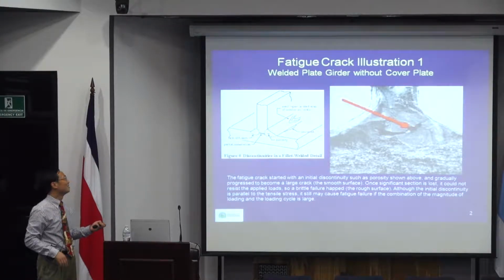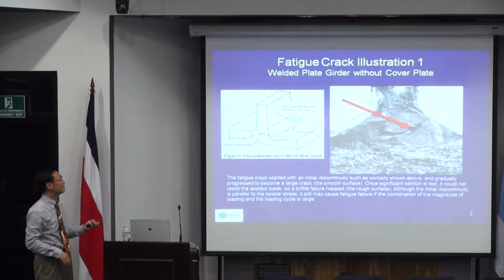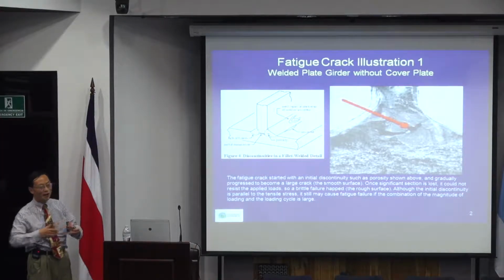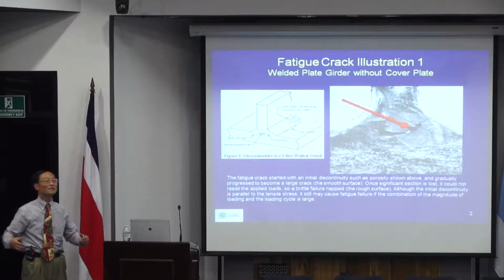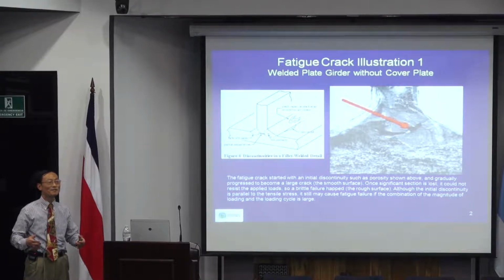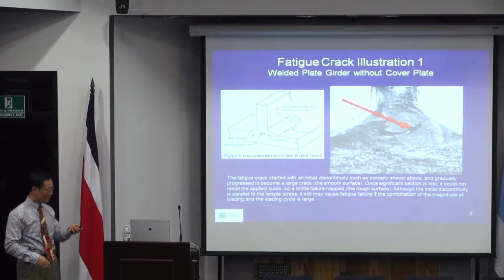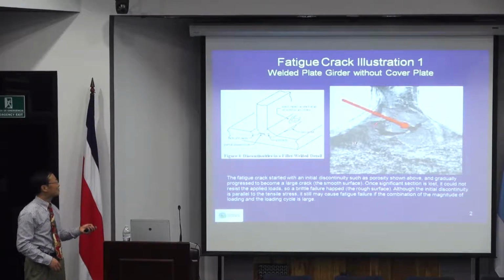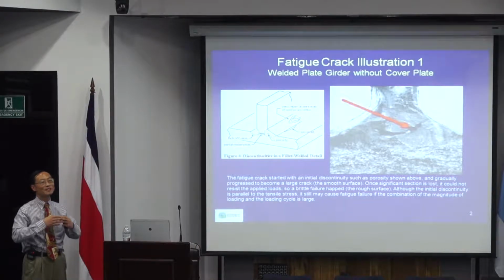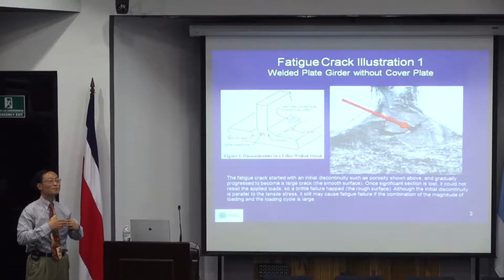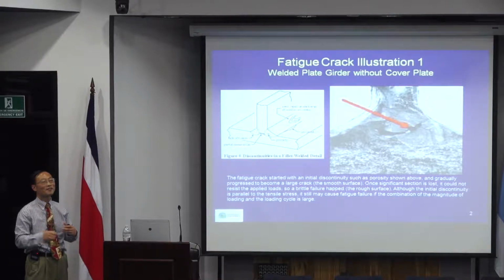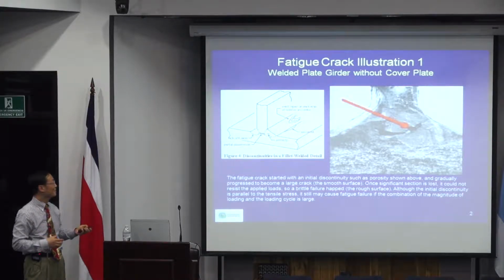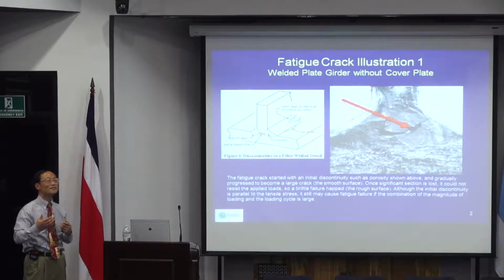Once you have thousands of cycles, the crack becomes bigger and bigger, and that's the plastic zone. Once the crack is so large, your section becomes smaller. All of a sudden, because the section is too small, it just breaks. And that breakage is not plastic. In other words, it's not caused by the plastic zone. So it usually gives you a very brittle, very shiny surface.